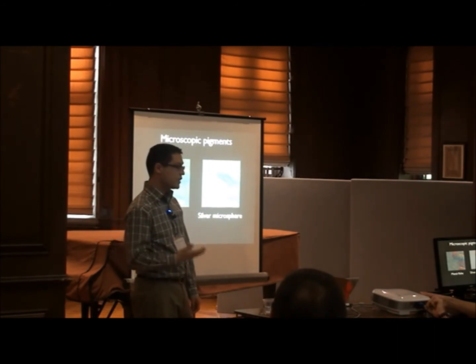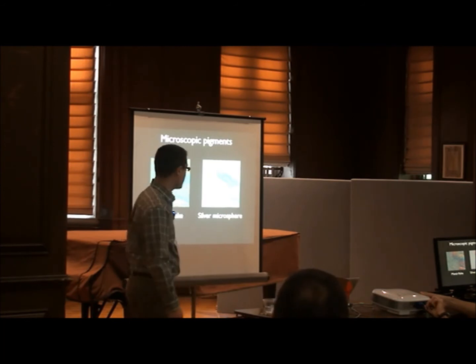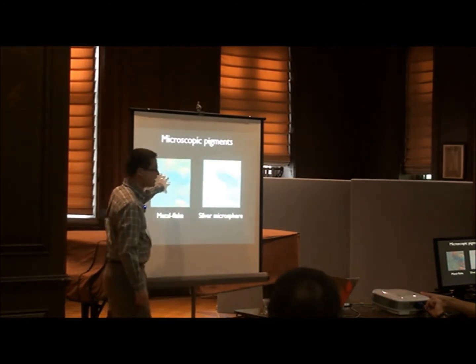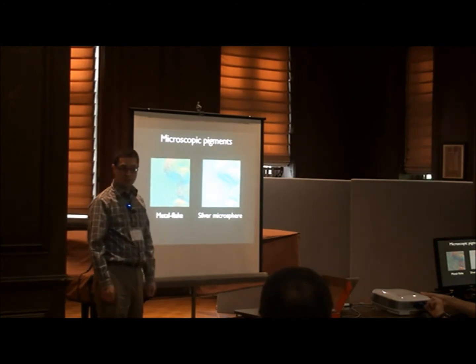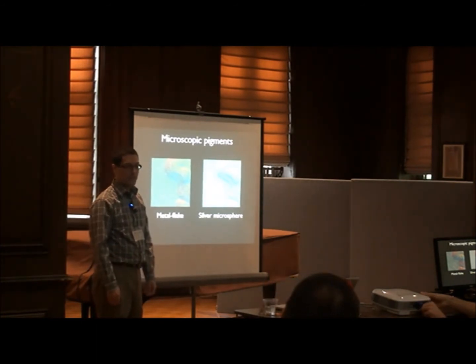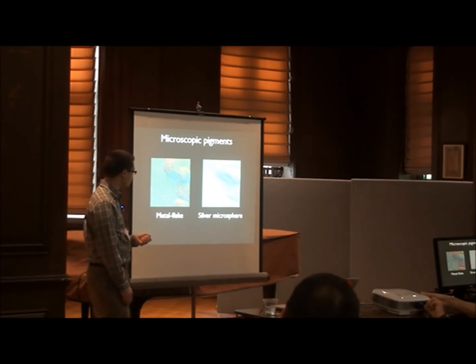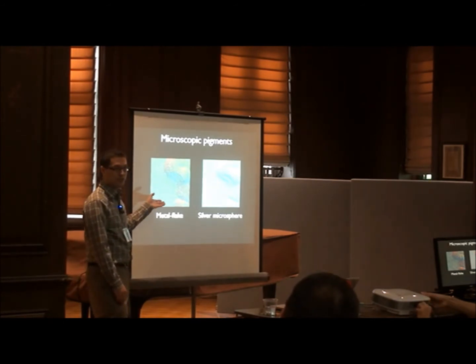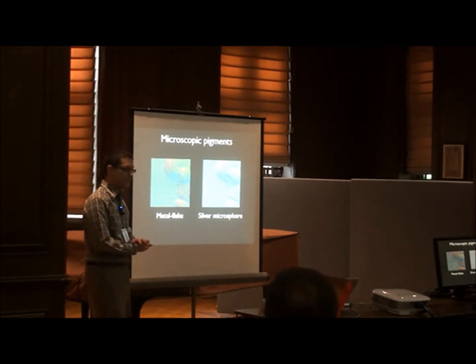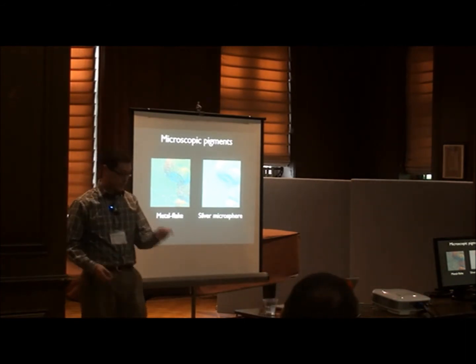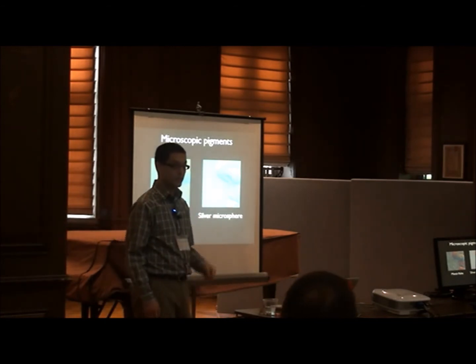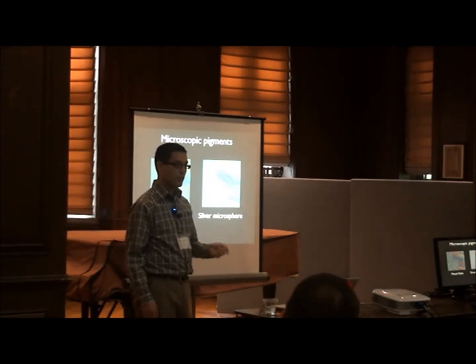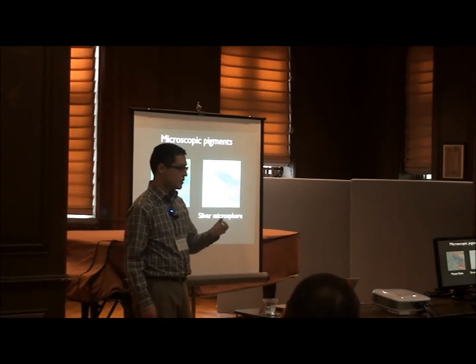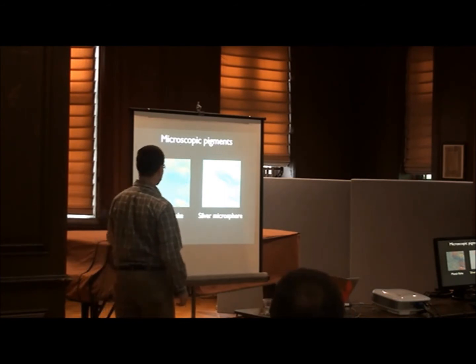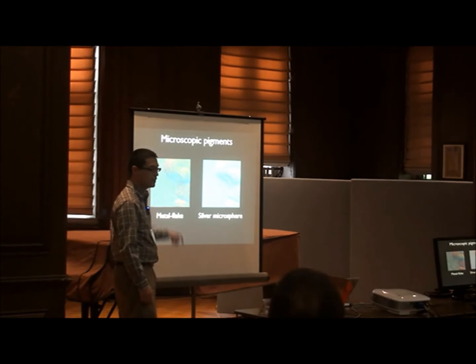And if you zoom in and look at it with even modest magnifications, you can see a lot of texture due to those metal flakes being at random orientations. And that texture would be measured because that's what you're seeing, right? And so this gets at the question of, what are we really seeing? Are we seeing the surface of the gel itself, or are we seeing the surface of the sample you want to measure? When we're using metal flake pigments at 20 micron flake size, you really are seeing a lot of the texture due to the gel itself.